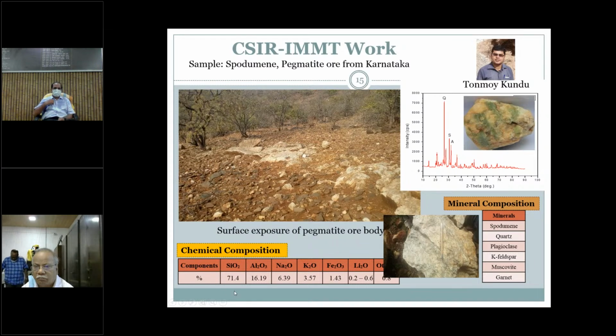It mainly contains silicates. About 71.4% is silica, alumina is about 16.19, sodium and potassium contents are varying here like this, and lithium content Li2O is varying between 0.2 and 0.6. Of course, we did not have much exposure, and in fact it requires some more exploration facilities to go deeper into the sample collection.